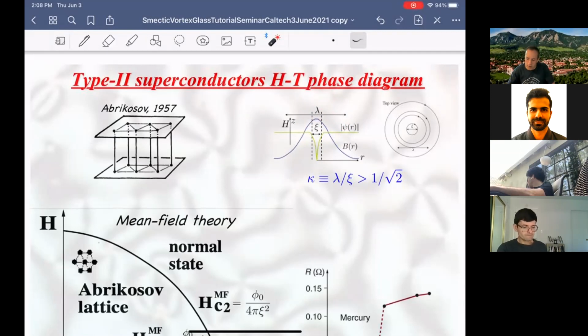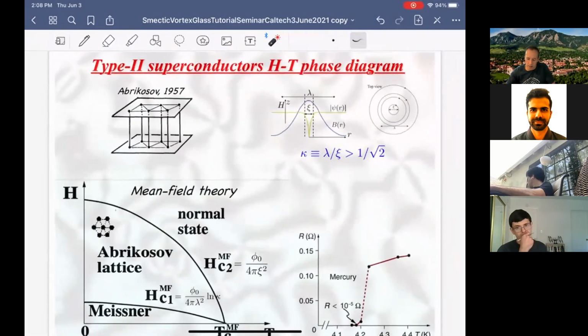And when you're in a regime where the magnetic fields are far stiffer to non-uniform distortion than the order parameter, then you're in this type 2 regime. In this regime, you start out with a Meissner effect in the superconducting state below Tc, and you apply a magnetic field. Rather than what happens in type 1 superconductors, where you immediately, via a first order transition, destroy the superconducting state and jump to a normal state, here there's an intermediate Abrikosov vortex lattice state, discovered by Abrikosov in 1957, where vortices do penetrate, but in terms of filaments of circulating currents, exhibiting these two length scales, ξ and lambda.